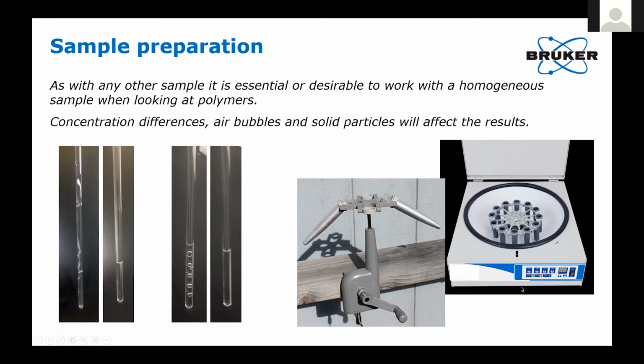Or if you have a fancy centrifuge like the one on the right, you can put it in there, you tape the tubes down to the hub in the middle, close the lid and spin it for maybe 30 seconds to a minute at less than 1,000 RPM, and it'll be fine.